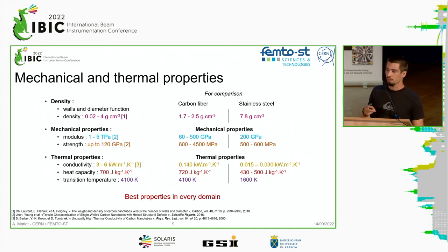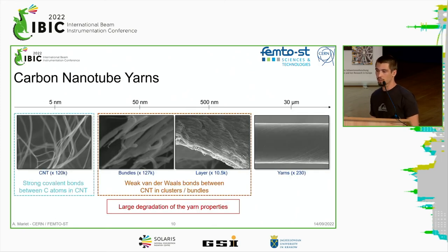But because of the nanoscale, we cannot handle them, we cannot manipulate them, and so far we don't have the technology to fix a single tube on our forks, on our instrument. And that's why we decided to focus our research on their microscopic assembly in a yarn. So the carbon nanotube yarns, or wires, are a structure at four different scales. First, we have the CNT, the carbon nanotubes, with a size of some nanometers. And these nanotubes agglomerate to form bundles. And these bundles entangle to form fibers. And finally, these fibers, or layers, we can spin them, and we can obtain the final yarn of 10, 20,